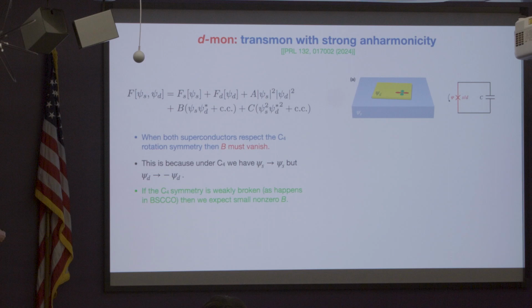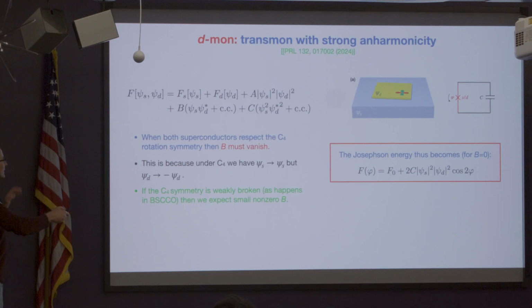It would map to minus itself, so it has to vanish. If C4 symmetry is weakly broken, as happens, for instance, in BSCCO, then we would conclude that this term is allowed, but probably is very small because it's a very weak breaking of C4 symmetry in a crystal like BSCCO. So I will continue with the assumption that this B is 0, but then I will bring it back later on to see what the effects are. So the Josephson free energy here looks like this. There's just a cosine 2 phi term, as opposed to cosine phi, which would be the conventional Josephson free energy.